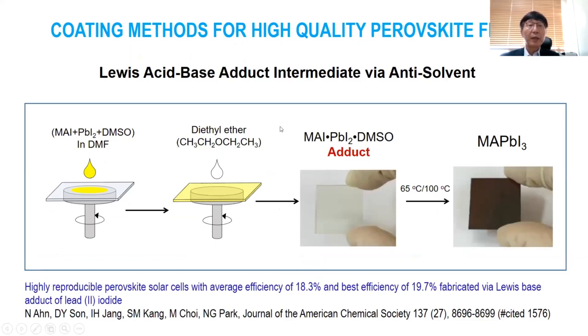now people frequently use the adduct intermediate method, which comes from the Lewis acid base adduct. For instance, if you drop the precursor solution on the spinning substrate, you have to include the DMSO, and then while spinning, you drop the diethyl ether, which acts as the anti-solvent, and then immediately you can get a transparent film, which is due to the adduct intermediate. And then after annealing, you can get the high quality MAPbI3. So the adduct can control the crystal growth of the perovskite film.